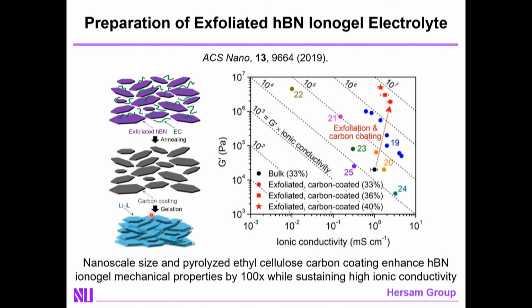One is that exfoliated hBN has high surface area, giving you more interaction with the ionic liquid. Additionally, we put an amorphous carbon coating on the hexagonal boron nitride that drives further interactions with the ionic liquid, giving us strong gelation and therefore high storage modulus without compromising ionic conductivity. This is useful for suppressing lithium dendrite growth in a solid-state battery.